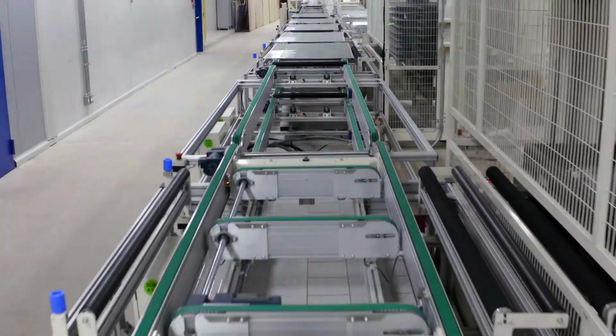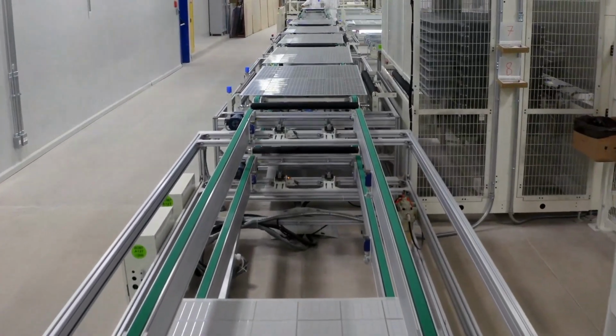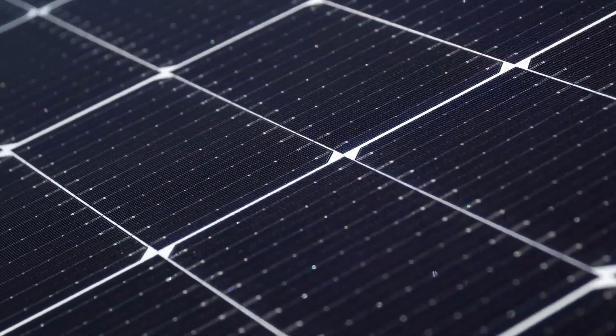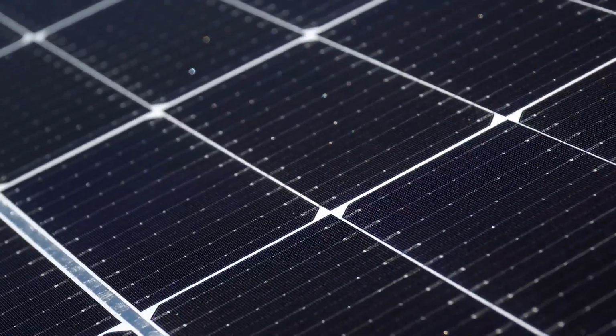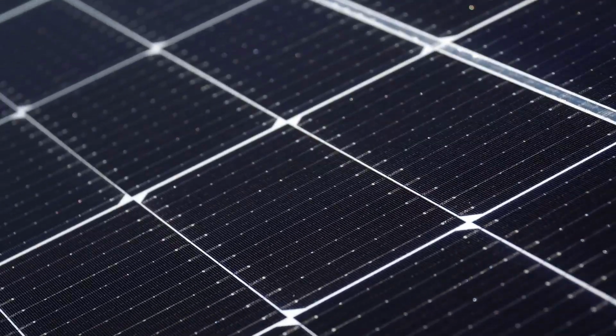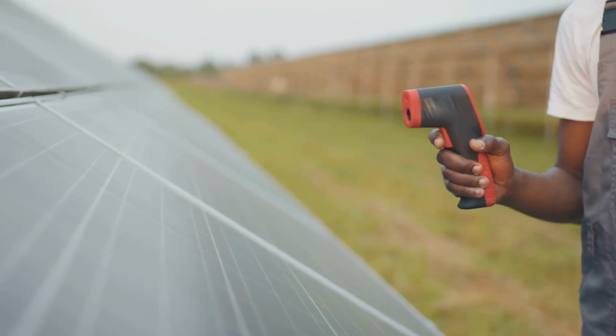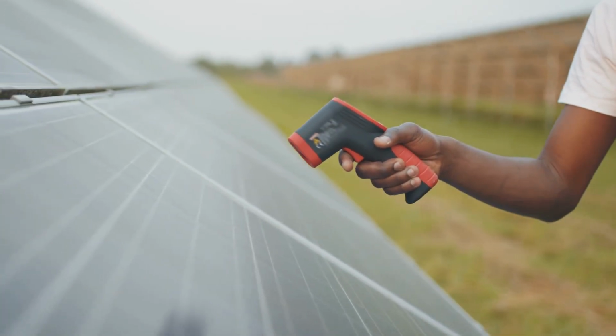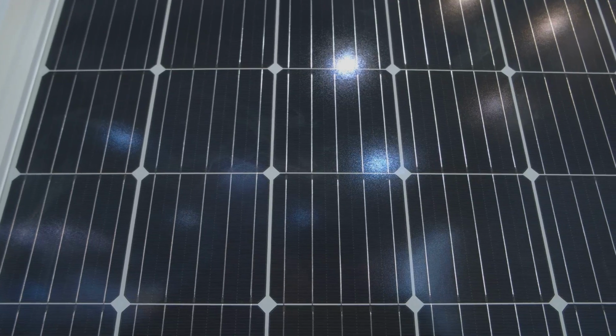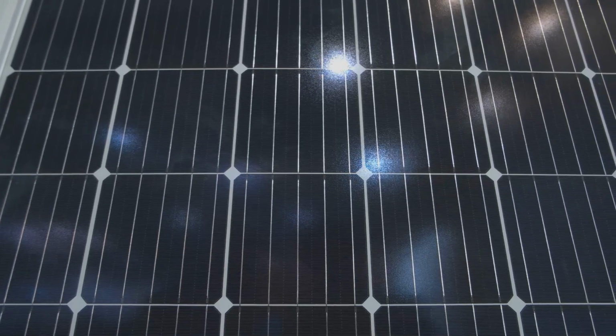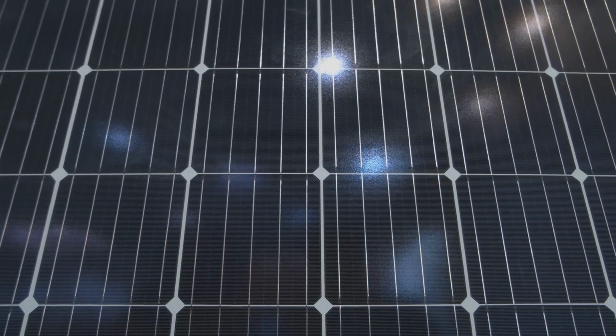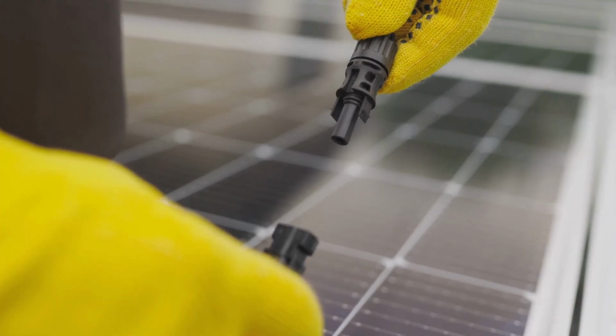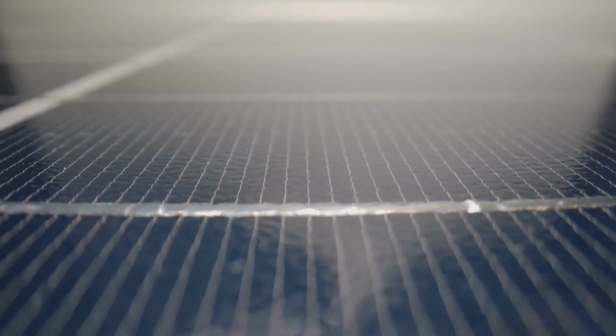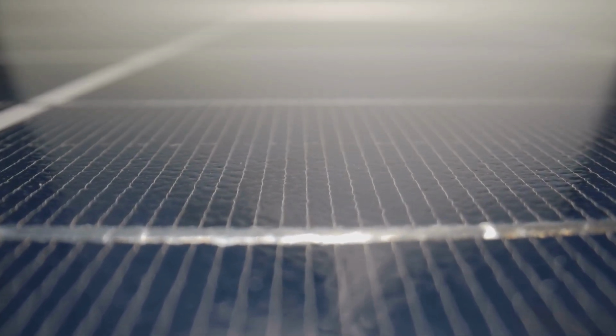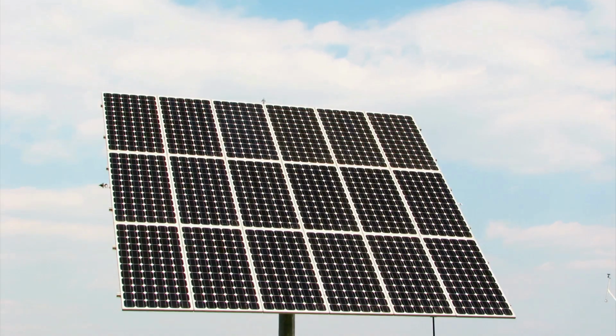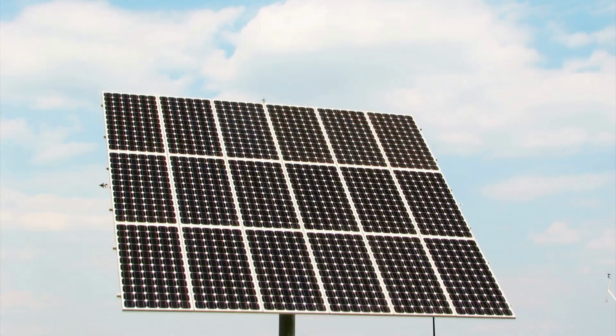Manufacturing is where many promising technologies struggle, and tandem cells are no exception. Perovskite layers must be uniform, defect-free, and consistently bonded to the silicon layer below. Even small imperfections in the perovskite layer can create electrical losses or lead to early degradation. Engineers also had to deal with ion movement inside perovskite materials, which can slowly reduce performance over time. This behavior made sealing the layered structure essential. Modern tandem cells use multiple protective barrier layers that block moisture and oxygen while shielding the active materials from heat and ultraviolet light.